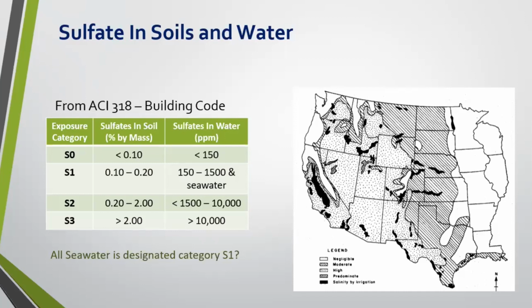An exposure category of S0 would be the lowest of these. And you can see by the chart, sulfates in the soil would be less than 0.1% by mass. In water would be less than 150 ppm, or parts per million. As you move down the chart and you get to an S3 exposure, now we're talking about sulfates in the soil in excess of 2%. But I'm assured there are situations in the US where these conditions do exist.